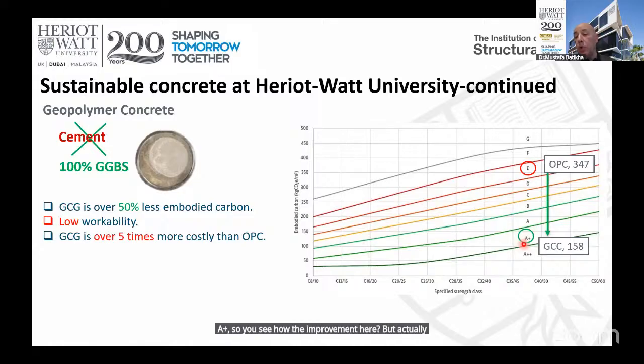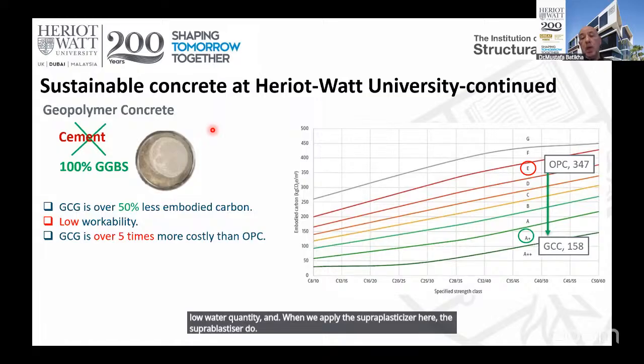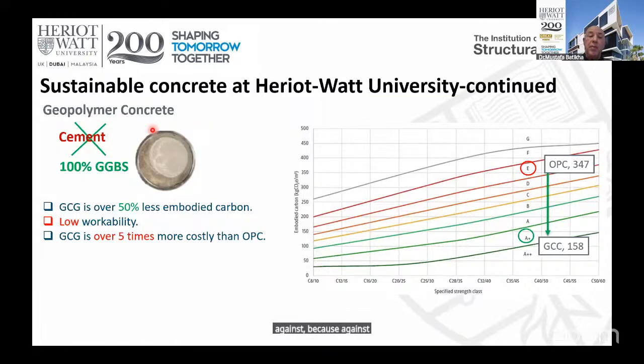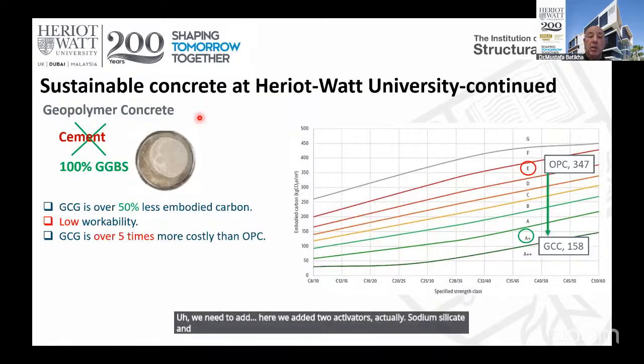But actually, we face two problems here with the geopolymer concrete. First of all, the low workability. We designed this product to reach 40 megapascal, so it has a low water quantity. And when we apply the superplasticizer here, the superplasticizer goes against the additives, because in geopolymer concrete we need to add activators. We added two activators, sodium silicate and sodium hydroxide. The sodium silicate works against the superplasticizer and stops its work.